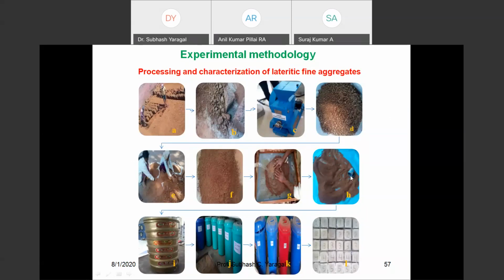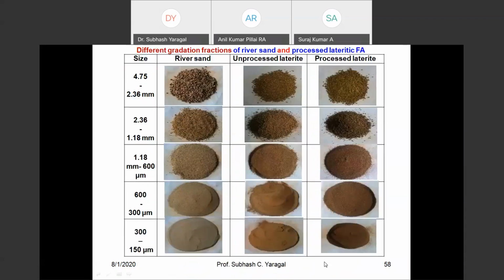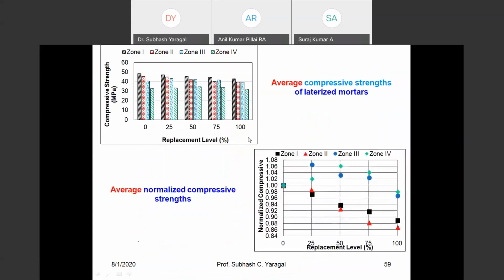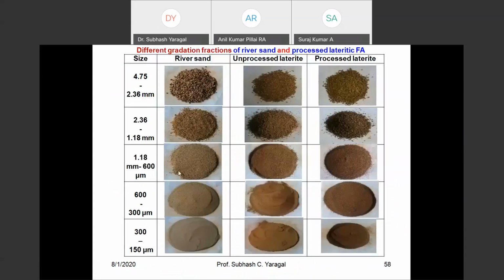After you do the sun drying, we have stacked them in various cylinders here. This is probably passing 4.75 retained on 2.36. This is passing 2.36 mm size but retained on 1.18 sieve, that way. And you can produce any zone of sand, and then we have used it in making mortar and concrete. So if you look at the different gradation fractions, this is for river sand, various sizes or fractions. Unprocessed lateritic sand will look like this, and processed laterite will look like this.